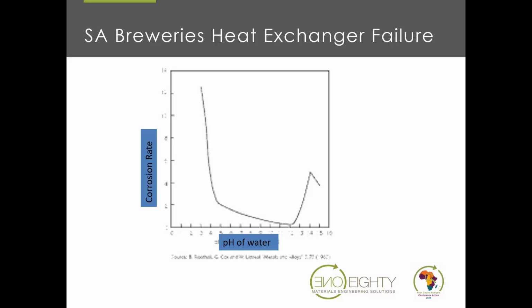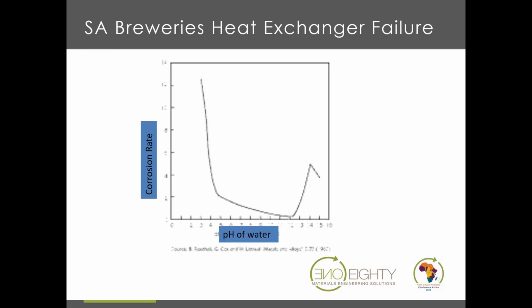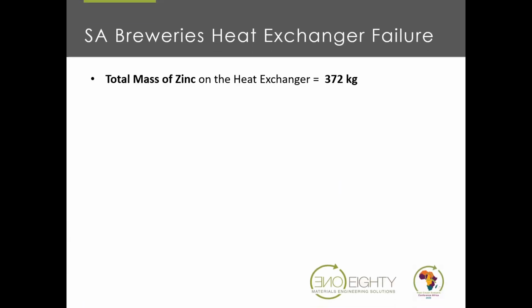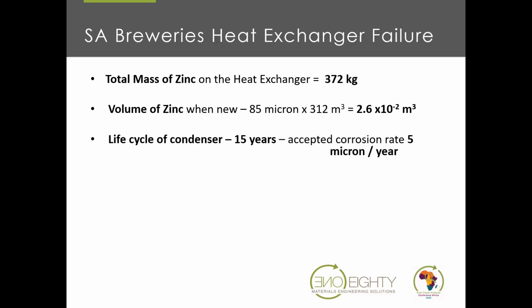I went back to my office, did some calculations, and thought, well, let's try to model that scenario and see what we get. Okay, so the total mass of zinc on the heat exchanger is 372 kilograms. The volume, we calculated to be this amount. It was just easier to do volumetric calculations than mass calculations. The life cycle of the condenser should be about 15 years, which meant that you could only lose 5 micron per year of the galvanizing.